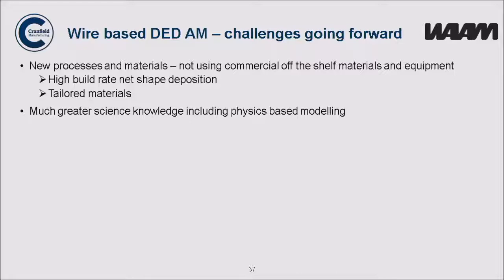Not only that, we're not using off-the-shelf wires. Now, when you do welding, you generally do one thermal cycle. When you do additive manufacture, you do several thermal cycles. The cooling rate is different, so you end up with a different microstructure. So the properties you get from welding wires are by no means optimum. So we want to tailor the design of the wire to match the thermal cycles that we have in the process. And this is surely going to be the next step forward, moving away from standard materials.